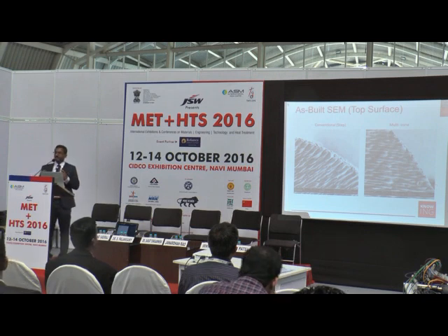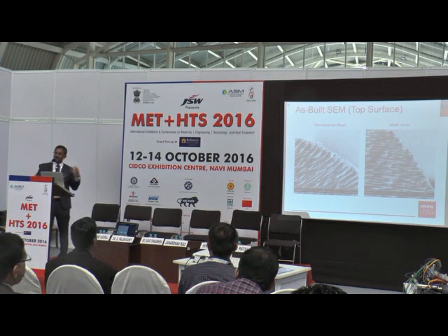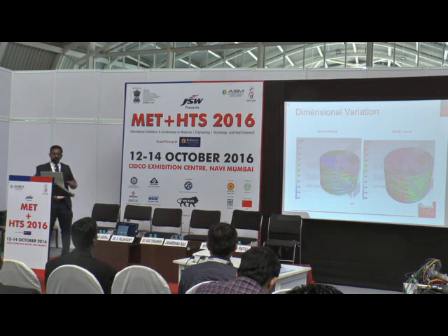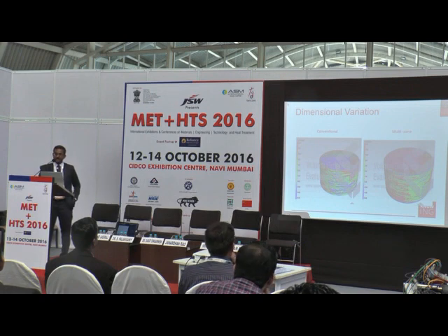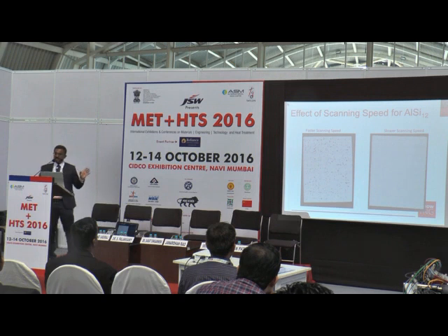So that's what you have to optimize: the scan strategy for the powder particle type and the component you want to manufacture. Again, this is a CT scan with a dimensional variation, which shows the multi-zone part looks far better than the conventional scan type. Again, this is a different sample.